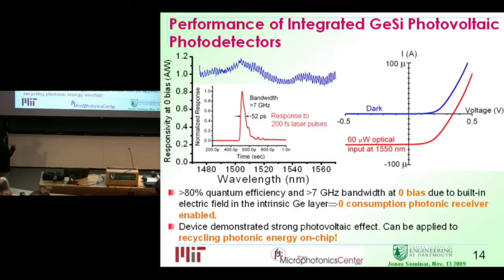You also want to know how fast this detector is. So you can shine a very short femtosecond laser pulse and monitor with very fast electronics to see what's the decay curve of the electrical response. And you measure a full width at half maximum of about 50 picoseconds. That's greater than 7 gigahertz bandwidth. And this is all measured at zero bias. So you do not need to bias the material to get this full responsivity. So it does not only not consume power, you can actually think about harvesting photonic energy from this device.